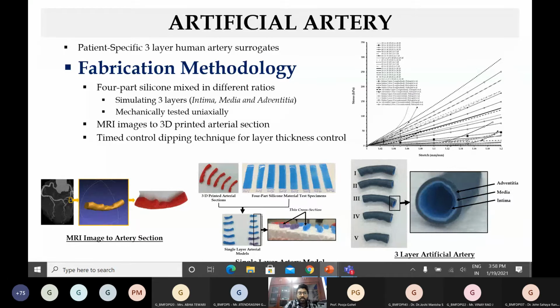The fabrication methodology includes a 4-part silicone, which is mixed in different ratios and comes with different compositions, with which we are simulating the 3 layers: intima, media, and adventitia. You can look at this very populated graph at the top. I have not zoomed this out because it's difficult to see, but I'll point towards some of the key highlights. We are basically trying to mimic the ranges of the intima, media, and adventitia tissue properties of the human artery using different hit and trial methods of different compositions. And we are trying to pinpoint which composition falls very close within this range. So that's what we have done. Very similar exercise to the human skin. So this is as far as the material is concerned.